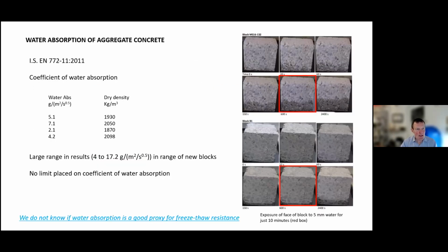Okay. Now, the importance of the water absorption of aggregate concrete is not lost, and there is actually a standard, I.S. EN 772 part 11, which determines the coefficient of water absorption. This is a simple test method, where you take a cube of concrete or a block, put it in 5 millimeters of water, and let the water saturate through the face for a 10 minute duration. So the red box is on the right. You can see that the two blocks I've shown have different uptake of water, but within 10 minutes, the water through capillary action has vertically risen to about a third of the height of that block on the top and much less on the bottom.